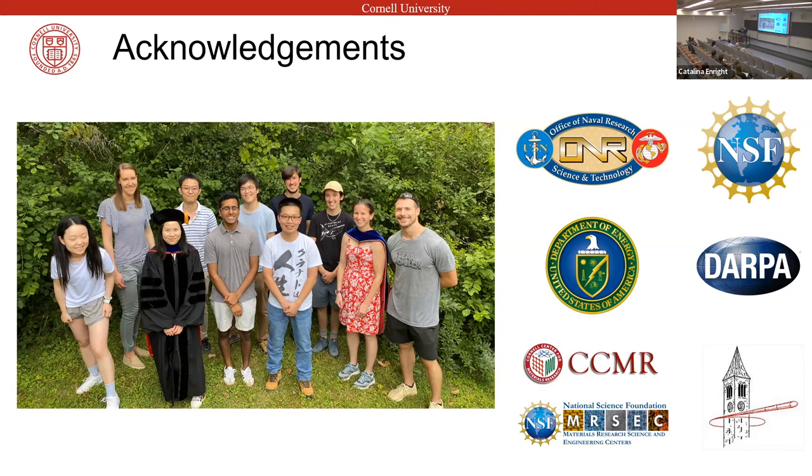As a sub comment, I do think if you do smaller scale microscopy on this, you would actually see inhomogeneities in that glassy. But one of the systems we've done this on is what I was postdocing on. We put it into polyurethane, which has domains that are much more rigid and much softer. We looked at the difference between how it responded in the soft and the hard, and some other groups have done things like that. So you could definitely use it to help understand stress distribution in different types of domains within a polymer. Well, I would think that would be a typical part of what stress relaxation is.